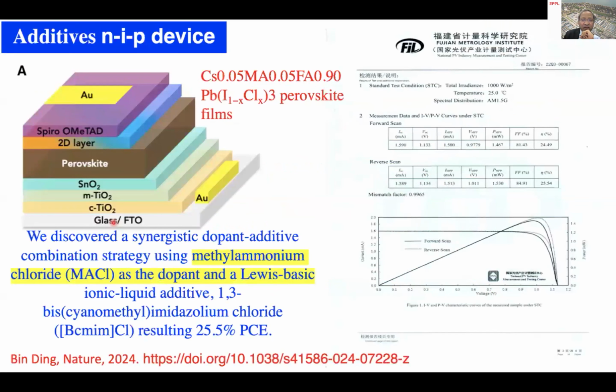So one example I'm showing here is an NIP device configuration, as I have mentioned before. What we have done in the perovskite composition is we incorporated methylammonium chloride. It's a simple compound, methylammonium chloride, and another ionic liquid. The name is given here. So what are this ionic liquid and methylammonium chloride doing?